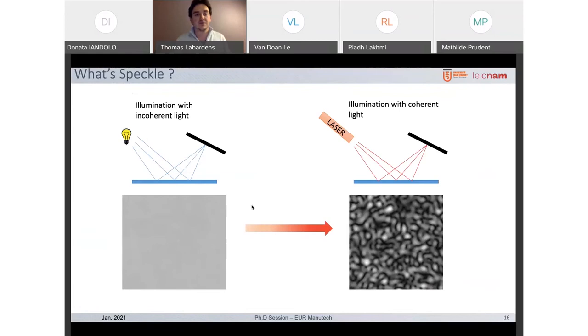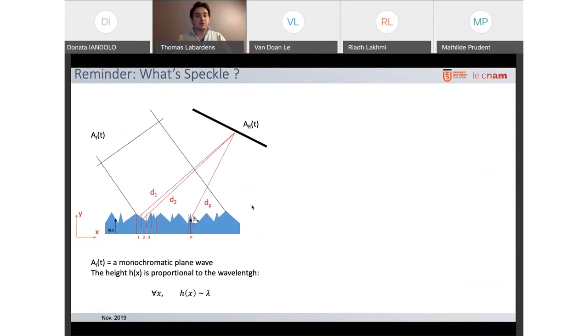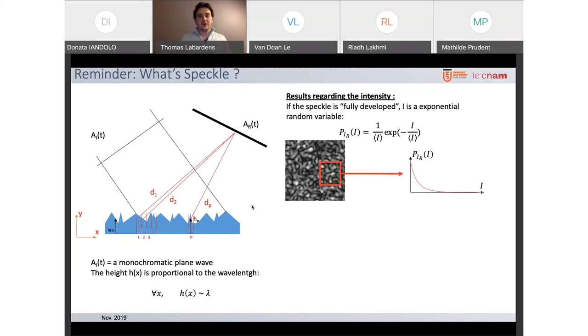So where is it coming from? Actually, you take a monochromatic plane wave, and you put it against a rough surface, and then you see what you get. If you have a plane wave and it's polarized, and then you want to see what you collect, you see what we call a fully developed speckle, where the intensity becomes an exponential random variable, because you get a random optical path difference, and that allows you to have this interference pattern. However, this fully developed speckle appears only if you have those particular conditions with a plane wave, a polarized wave, if the surface doesn't have any spatial property.